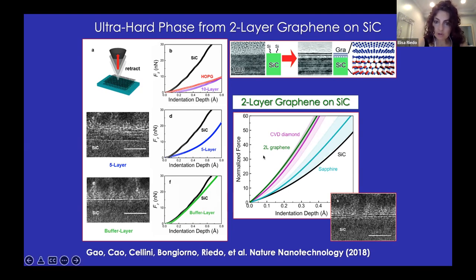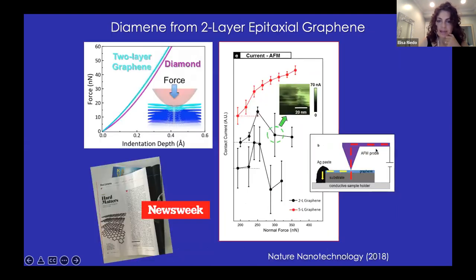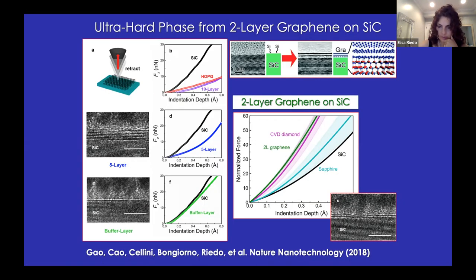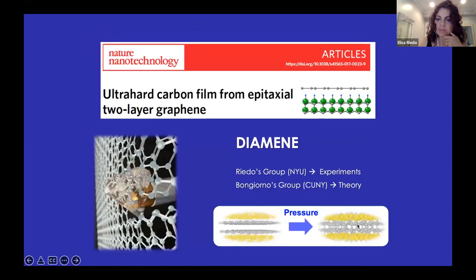So when we measure this type of system, as you can see here, we get a stiffness that is much higher than silicon carbide, higher than sapphire, and close to the stiffness of bulk CVD diamond. In order to explain this, we work with theorists who run some molecular dynamics simulations and DFT simulations, and indeed the simulations prove the formation of a single layer diamond.